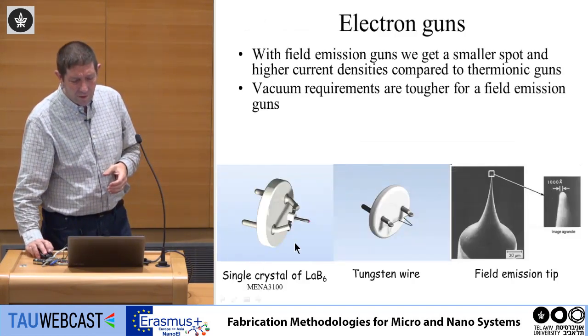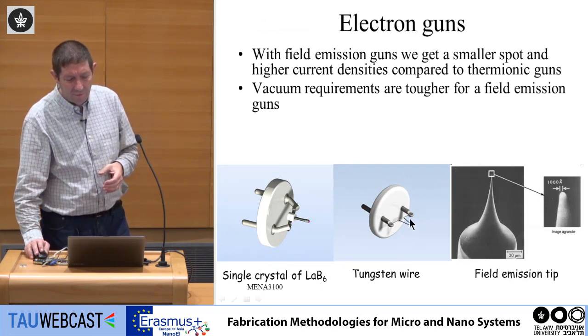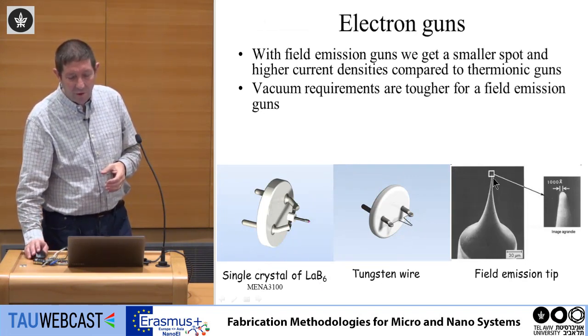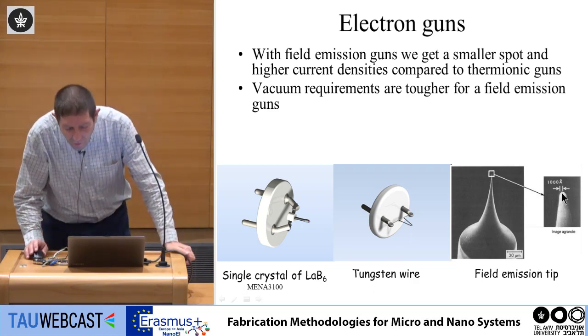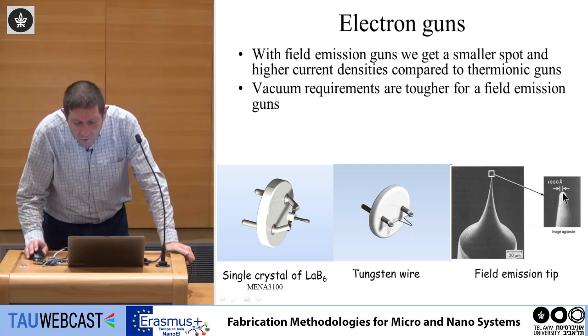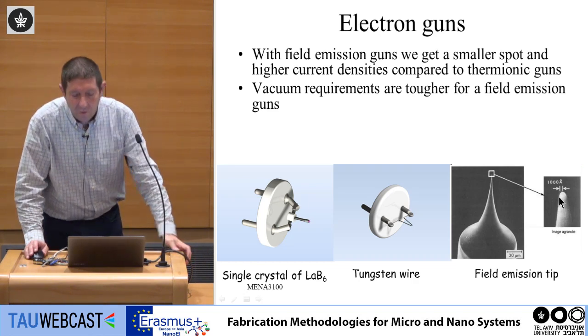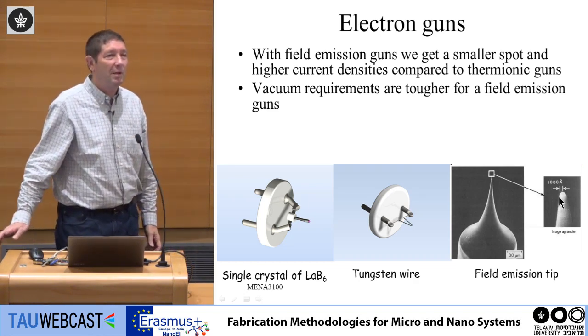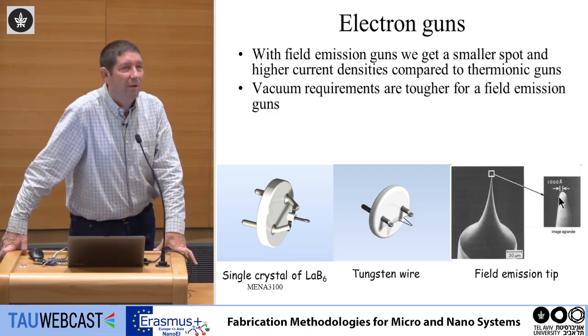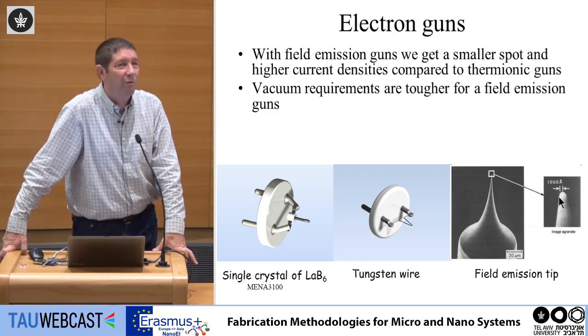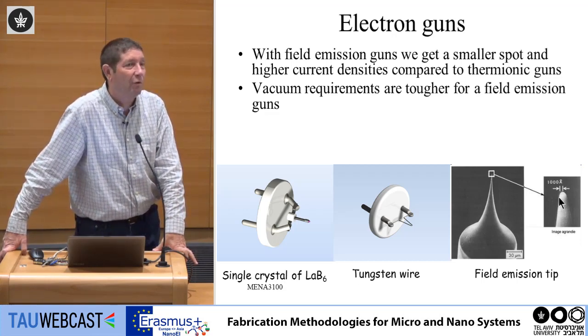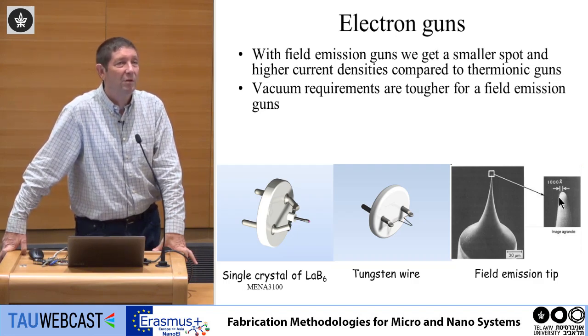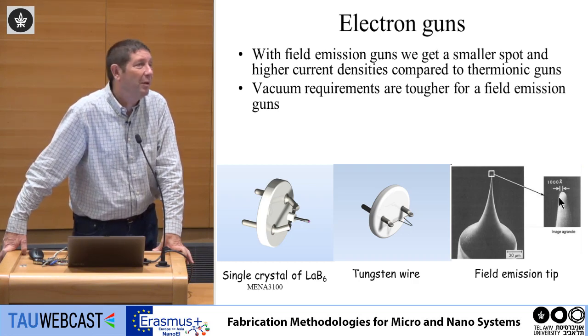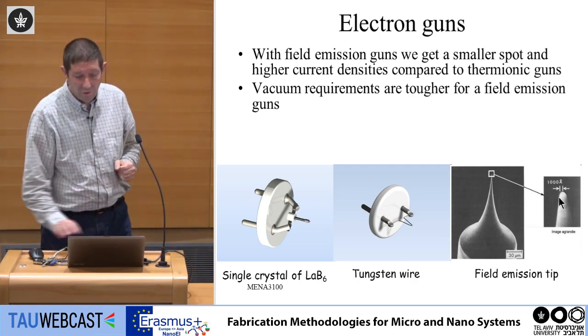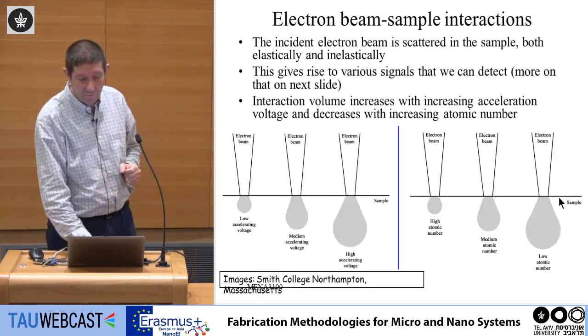How do they look? Either single crystal LaB6, tungsten wires, and field emission tip, this is how they look. And this one has a 100 nanometer tip. So in a 100 nanometer tip, which is 10 to the minus 5 centimeter, if you want to have an electric field of 10 to the 7, you have to apply about 100 volts. Because 100 volts is 10 to the 2 divided by 10 to the minus 5, which is 10 to the 7, which is not so bad. It's not such a high voltage. So this is what you do to get field emission.